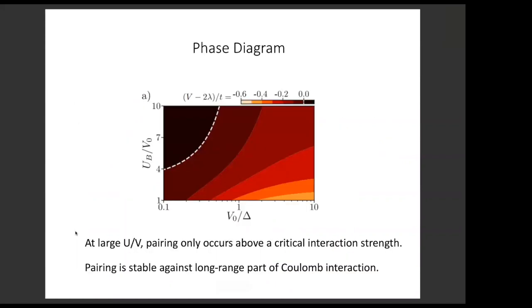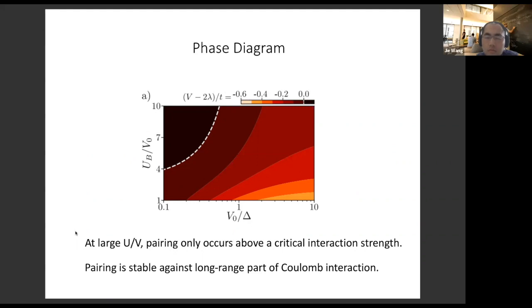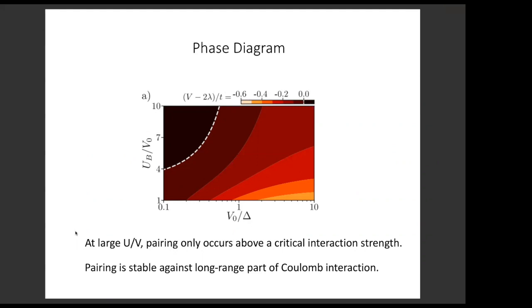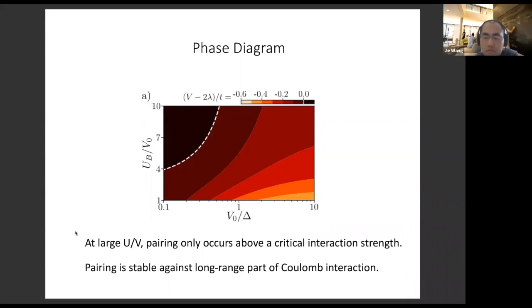Next slide. So this is the phase diagram. You see that this white dashed line separates the superconducting and non-superconducting regions, or regions with and without attractive pairing interaction. If the on-site U is large, then you need the repulsion V to be above a critical value to enter the superconducting region. Therefore, it is essential that this theory is non-perturbative in interaction strength. Also, we checked that even at the level of two doped electrons, the bound state formation is stable against long-range Coulomb interactions. If we include further long-range interaction, the bound state is still there over a finite range of interaction strengths. Next slide.